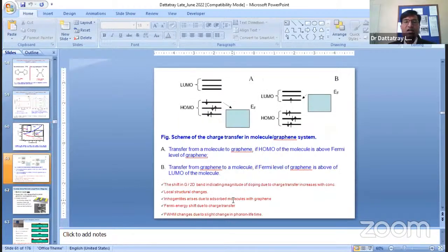So what happens here when you add this TTF or TCNE is the transfer of charges from molecule to graphene, if the HOMO of the molecule is above the Fermi level of the graphene. You can see the electronic band structure positions: the LUMO is on this side, the Fermi level is on this side. When charge transfers from graphene to a molecule, if the Fermi level of the graphene is above the LUMO of the molecule, of course you can monitor the shift in the G band as well as the 2D band.